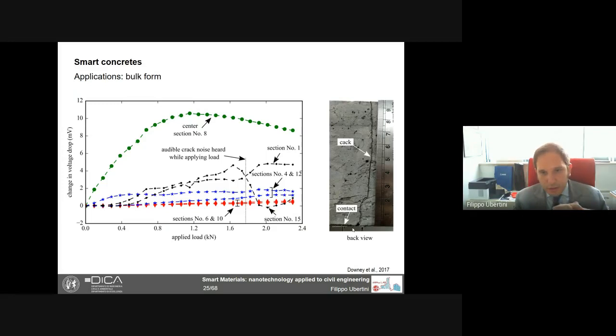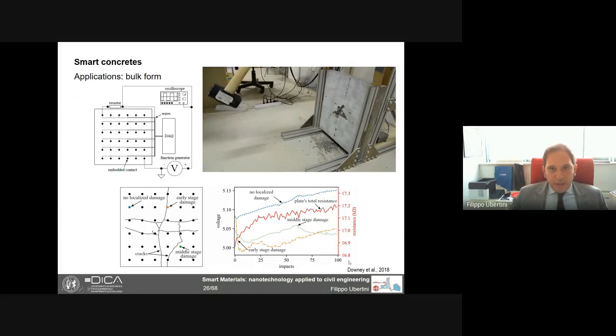And the third thing you should notice is that at a certain point, when we are around 1.6 kilonewton, there was a shear crack forming out of the electrodes. And section number 1 and section number 15 show an opposite behavior. One was increasing in drop, the other one was decreasing. And for sure, we have some bifurcation. We have some dramatic change in the electrical behavior of this section. And we will see later on that this is actually associated to the damage, and we can predict it with a numerical simulation.